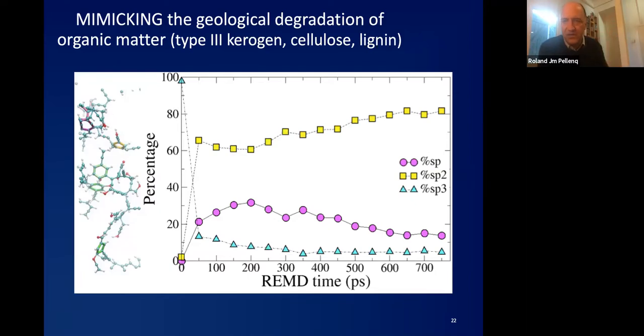And actually, if you look at the chemistry of carbon, there are three ways. Either a carbon has 2 neighbor carbons, it's called sp bonding, or a carbon has 3 neighbors, like in the ring, this carbon ring there. It has 3 neighbors with very defined 120 degree angles, or a carbon atom can be bonded to 4 other carbons. This is sp3, and this is typically what we have in diamond. Diamond is carbon, right? But it's not graphite. Graphite is purely sp2, diamond is purely sp3.